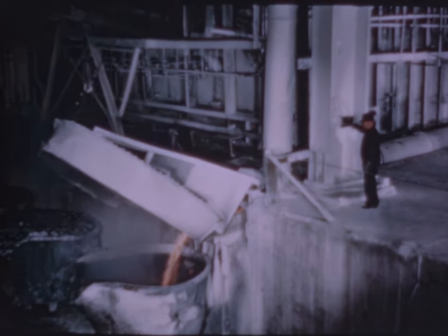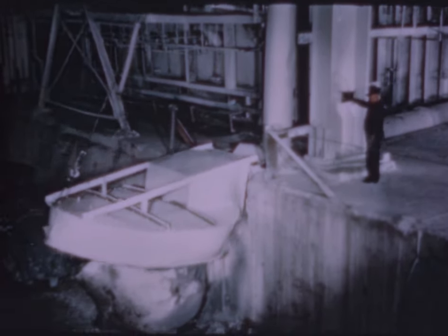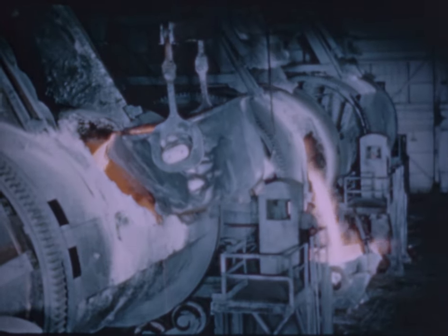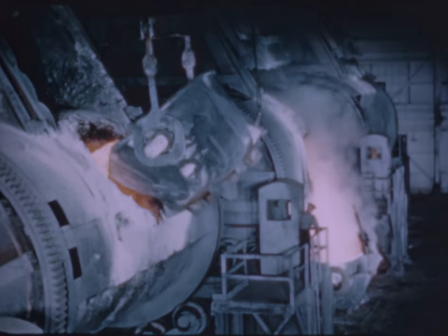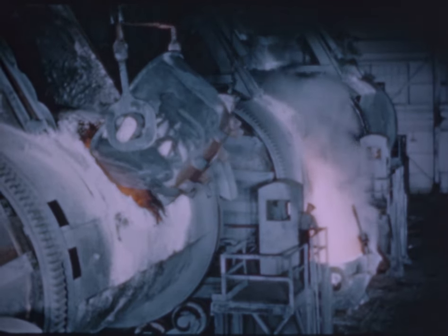The copper sulfide and iron sulfide form a mixture called mat, which sinks to the bottom of the furnace and is tapped periodically. This molten matte, containing from 45 to 50% copper, is transferred in ladles to the converters. The function of these giant converters, which hold 120 tons to the charge, is to remove the iron and sulfur from the matte, leaving metallic copper.